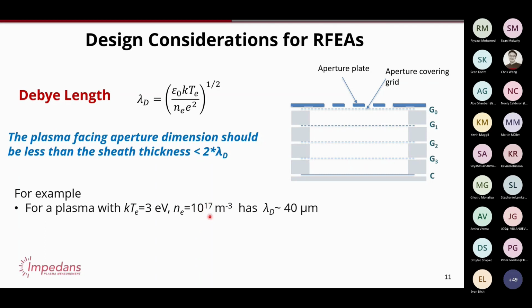So this is sort of the middle of that range. That would be a 40 micrometer Debye length. So that means that this aperture here needs to have a plate or a mesh behind it with the spacings of this grid less than maybe 80 microns. In the sensors that Impedans produce, we use about 20 or 30 microns distance there. That prevents most plasma from getting in.